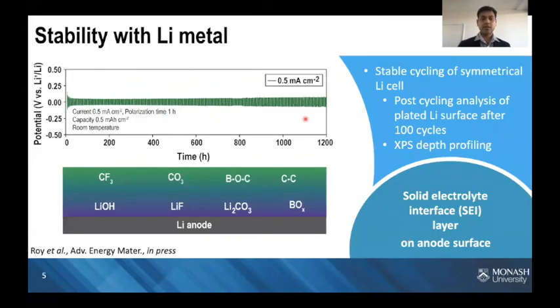Here, what we have done is understand the compatibility of this salt against lithium metal. To do that, I constructed a symmetrical lithium cell with the carbonate electrolyte of our novel lithium BHFIP salt, and I cycled it for up to 1200 hours or 600 cycles. The symmetrical cell cycling didn't show any dendritic formation or any abnormality, suggesting the borate salt is perfectly suitable for lithium metal battery applications.